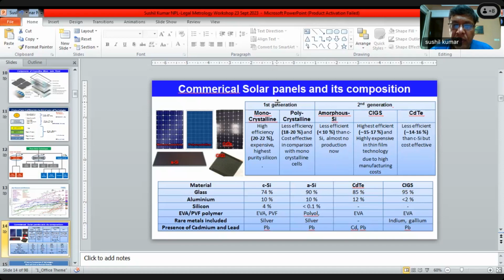In monocrystalline or polycrystalline, basically the silicon comes from the normal sand, that is quartz, SiO2. You need to heat it to more than its melting temperature, 1800 to 2000 degrees Celsius, under a carbon atmosphere, so that you can have metallurgical grade silicon. Metallurgical grade silicon is used in many other applications, in various alloy formation and in rubber industries. Hardly 10% goes to semiconductors, which include microelectronics and solar cells.